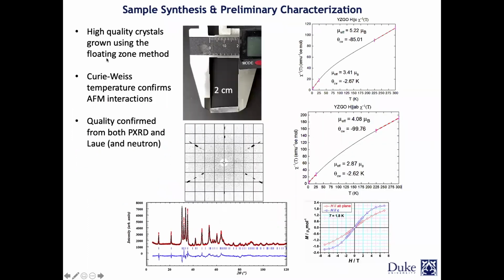In the case of ytterbium zinc gallium oxide, we also use this technique. Here you're looking at the single crystal of this compound. The whole thing, about 2 centimeters, is one single crystal. And here you're looking at the X-ray Laue pattern of it. You can see that it's a very nice hexagonal pattern, and all the peaks are very sharp. So it's a very high quality single crystal.